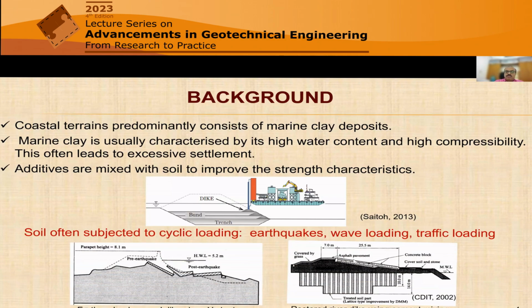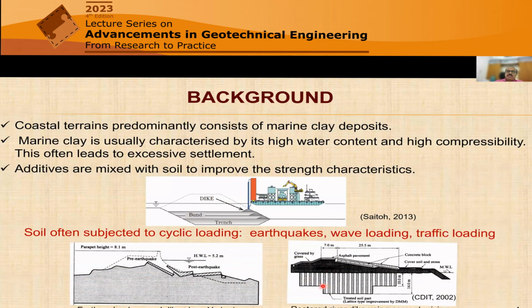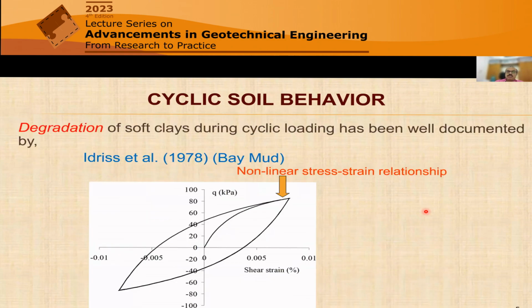But if you see this particular case, which is a dike in Japan, it's constructed over cement treated ground. It's basically DSM columns, deep soil mix columns, and it suffered significant damage during the 2011 Fukushima earthquake. So it may not be appropriate to assume that cement treatment alone is fine for any kind of situation under dynamic loading.